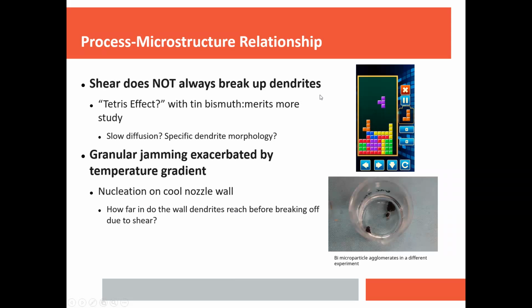So what he observed was under high shear and maybe under a temperature gradient, tin bismuth tended to... Usually in a semi-solid metal alloy with dendrites, you break up the solid particles into smaller particles in a high shear mixer or some mixing system. And the breakup of the dendrites improves the flowability and the material properties at the end of semi-solid metal processing. For tin bismuth specifically, for whatever reason, under the right conditions with high shear, the dendrites actually grew, which was very interesting. That's generally not considered possible in that field.